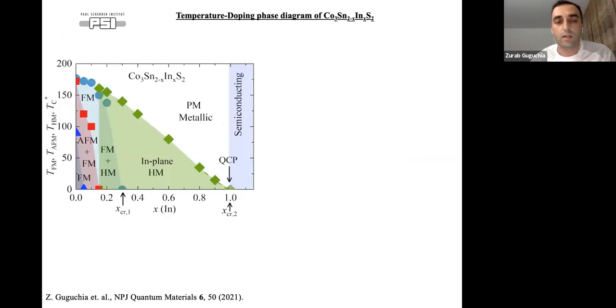Without really telling you all these details of the measurements or the analysis, we can now summarize the data in a temperature-doping phase diagram. And we can see that as a function of indium doping, we get a much richer phase diagram than with pressure. We can suppress the ferromagnetic state at very low indium doping. Then we have the mixed phase, antiferromagnet plus ferromagnet. But finally, we end up in this helimagnetic state, with only in-plane incommensurate helimagnetic ordering. So within about 0.3 concentration of indium, we are suppressing both the antiferromagnetic and ferromagnetic states, and we end up in the in-plane helimagnetic state.